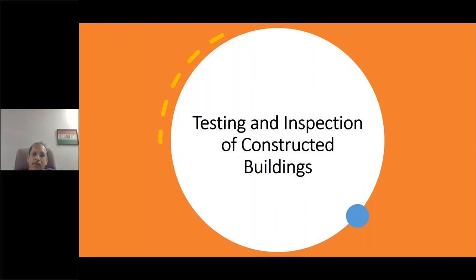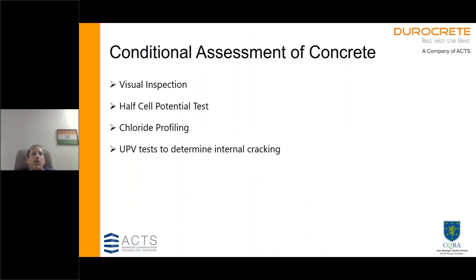Many times the buildings are not inspected, or there is a lot of cladding inside the building. Sometimes the flats are sealed and not available for inspection, and heavy deterioration goes unnoticed. So when we talk about conditional assessment of actual buildings, we generally adopt these measures: visual inspection, half cell potential test, chloride profiling, and UPV test to determine internal cracking. The visual inspection is the most important test, and if you do a regular visual inspection, the majority of failures or collapses can be prevented.